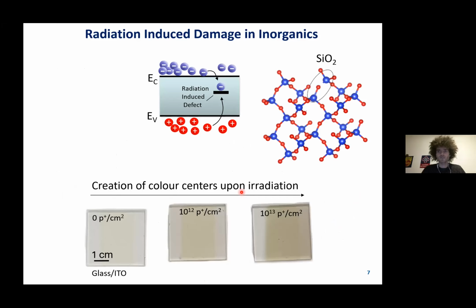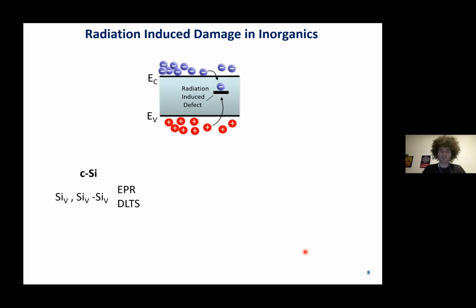And I'd like to start with just glass, which we all use as a substrate for our solar cells, right? So silicon oxide, in silicon oxide, you start to form these color centers when you break a silicon-oxygen bond. And this darkens your glass. And this, of course, affects any solar cell behind that glass. It also affects crystalline silicon, which we use in transistors and silicon solar cells. And here people already know that you start to create these silicon vacancies. You can see them by EPR and DLTS measurements.